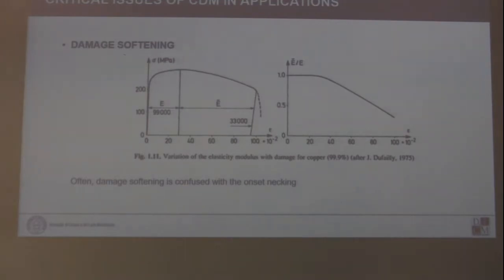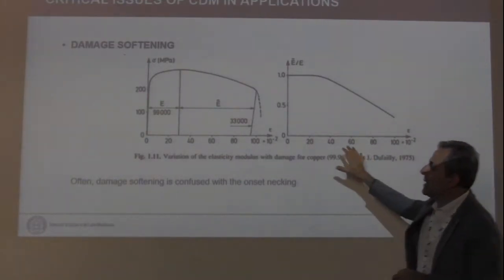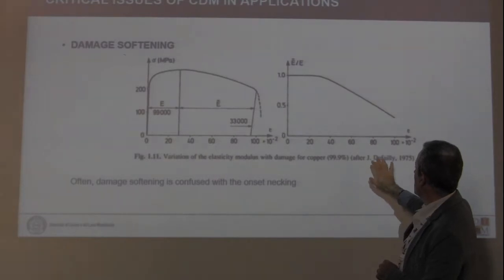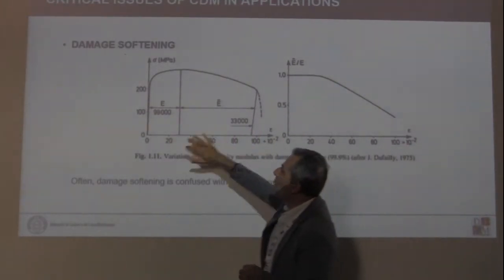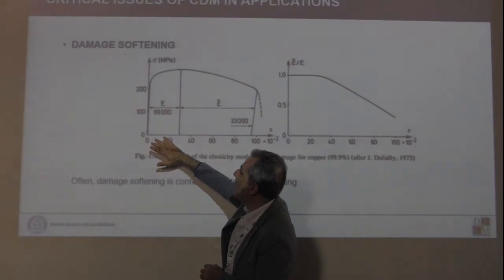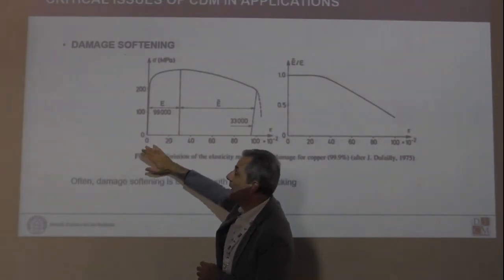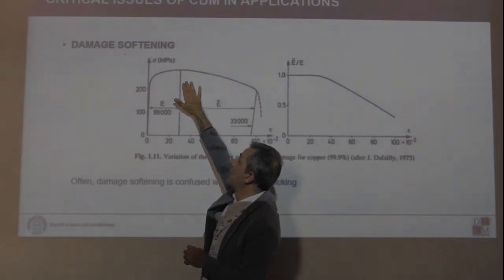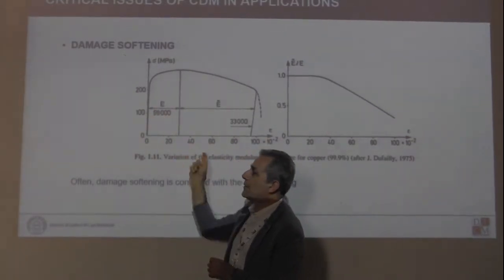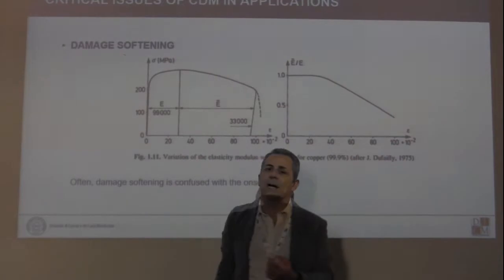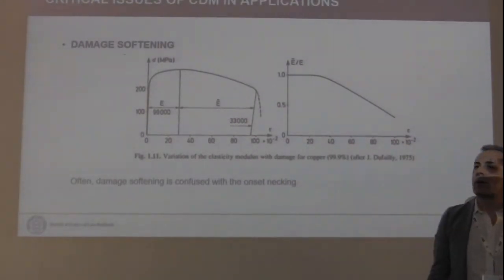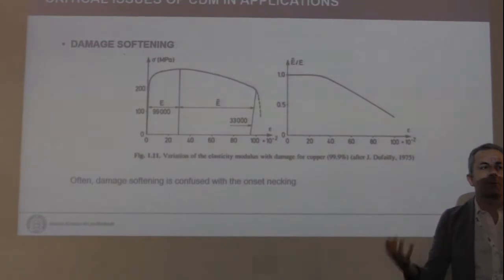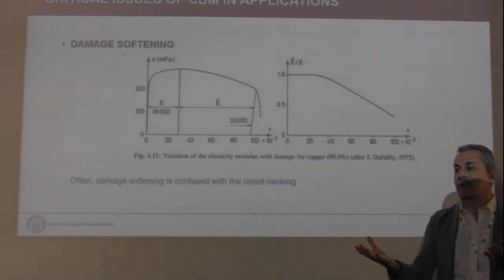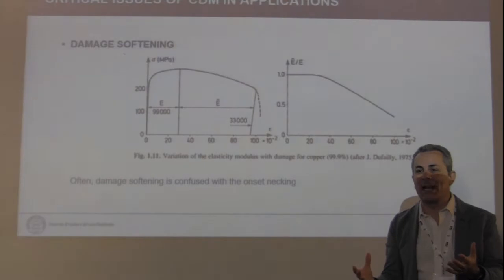There is a big misunderstanding in the continuum damage mechanics history. This is a paper by Dufailly and the French school. They were identifying the initiation of damage as soon as the response of a tensile sample starts to go down, but in this way they were completely neglecting the fact that this was just a geometry response. So this is necking. It's a plastic strain development for ductile material. It has nothing to do with damage.